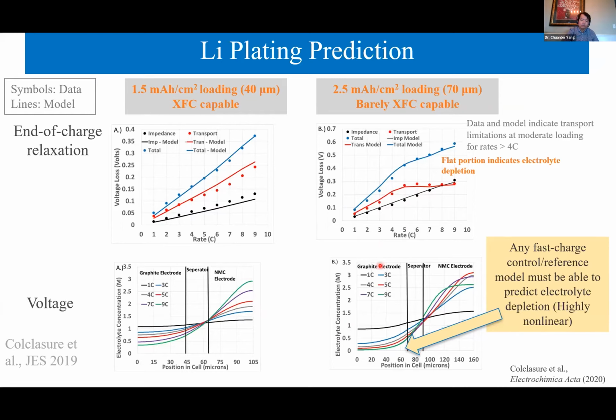Extreme electrolyte concentration results in very sluggish lithium transport and poor electrode utilization. For the low loading cell, there's enough electrolyte diffusion to prevent electrolyte depletion in the anode phase, even up to 9C. However, for the moderate loading cell, electrolyte depletion actually occurred within the anode at 4C and beyond. Thus, at rates higher than 4C, insufficient electrolyte transport results in severe transport losses and non-uniform electrolyte utilization for the moderate loading cell.